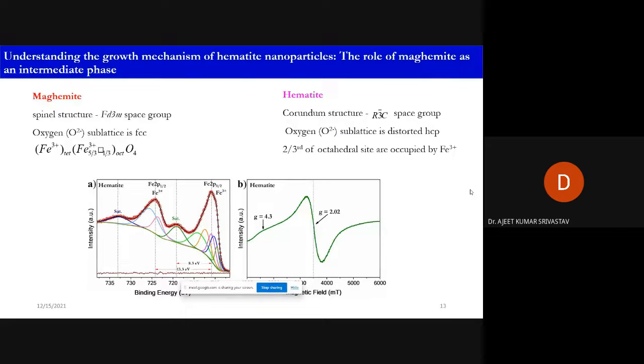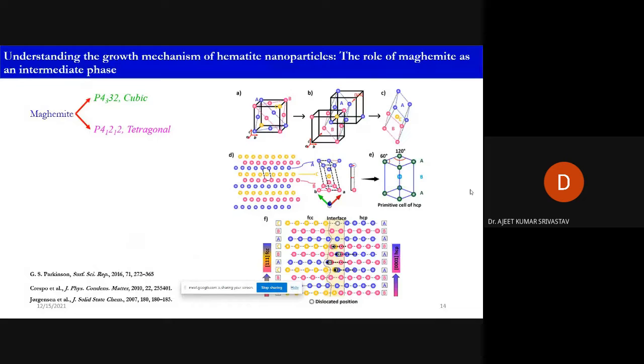So phases are confirmed, pathways are confirmed. Now we'll try to understand how the transformation is happening, okay? Maghemite comes with 2 possible space groups. One is cubic, and another one is tetragonal, based on the level of vacancy ordering. So if you see the right side, for easy follow-up, we have only discussed the oxygen ion sublattice, how it is transforming from FCC to HCP. We have made it clear here how 2 FCC unit cells combine and finally form the tetragonal maghemite.